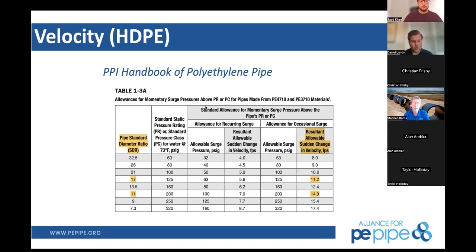Yes, Stephen. So just to make sure we're all understanding this correctly, we have a working pressure, and that working pressure does not have to be derated unless we are going past these high velocities, correct? Exactly. In this case, for polyethylene, pressure class does equal working pressure rating, unless you're going over 14 feet per second flow, which most municipal systems won't. Some industrial applications might, but most municipal systems are limited to 8 feet per second. So you can see here, you don't need a PC 200, even though a lot of people use it. If you're operating at 125 PSI, you can use a DR17. Now, there may be other reasons you don't want to, but for pressure rating and surge capability, it can handle it all day long.